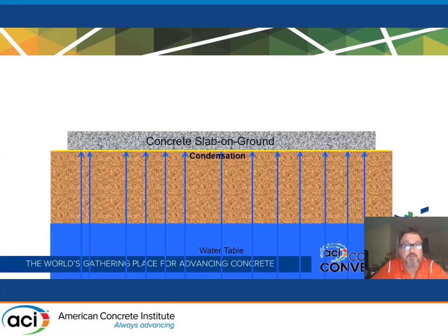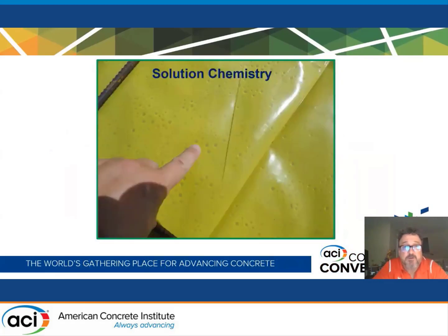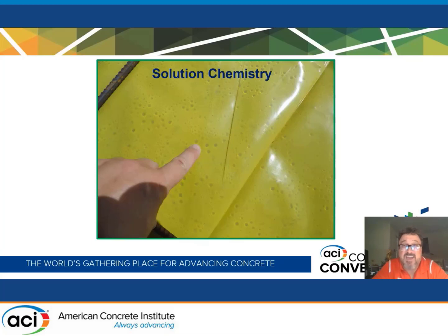Here's a shot of an effective vapor retarder with very low permeance, and here it is doing its job. You can see that the condensed vapor underneath the vapor retarder — if there are sulfates in that soil — results in a very high concentration of sulfates in the liquid water beneath the vapor retarder. But it's not in contact with your concrete. So you've achieved a Category S, Class S0 — sulfate exposure class zero — by using an effective vapor retarder.